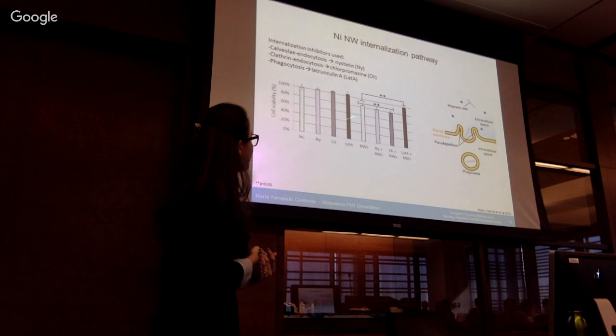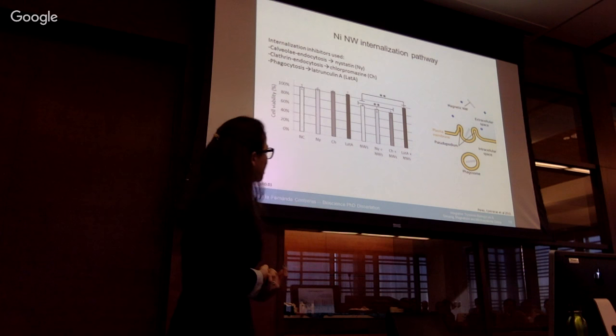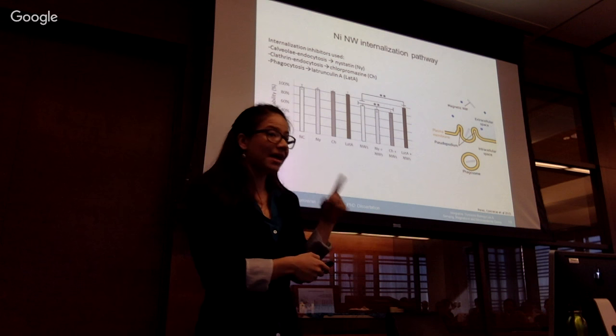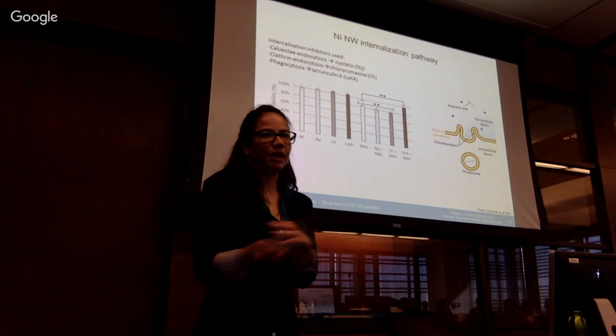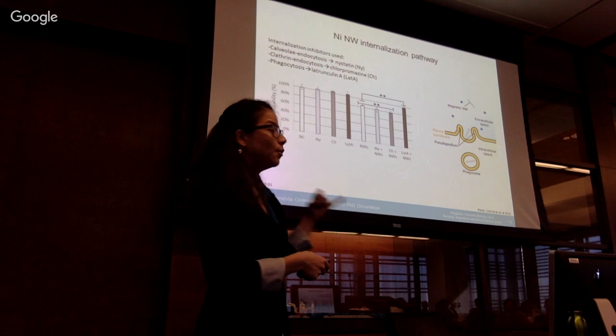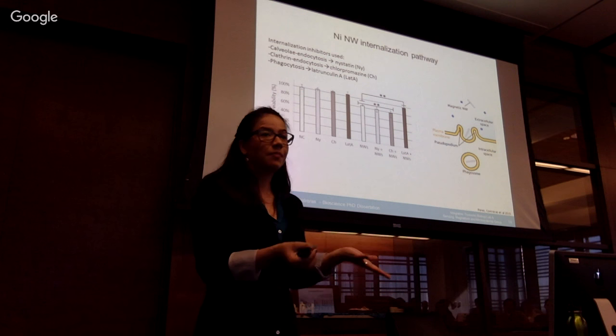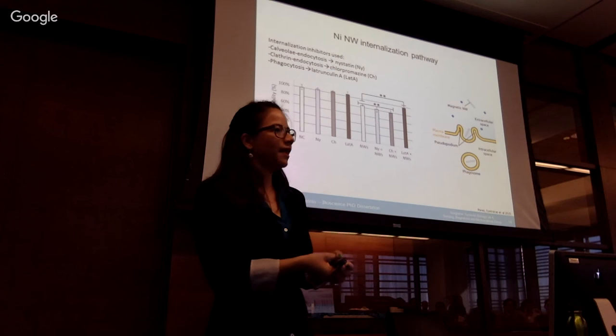So the reasoning behind this was, okay, if we add the wires and the inhibitor, and we measure the same viability drop as when we culture with only the wires, that means the wires are getting inside nevertheless. So the inhibitor is not impeding this internalization process. However, if by adding the wires and the inhibitor, we go back to the condition with no wires, then that means this inhibitor is actually blocking the internalization of the wires, and that's the pathway the nanowires follow.